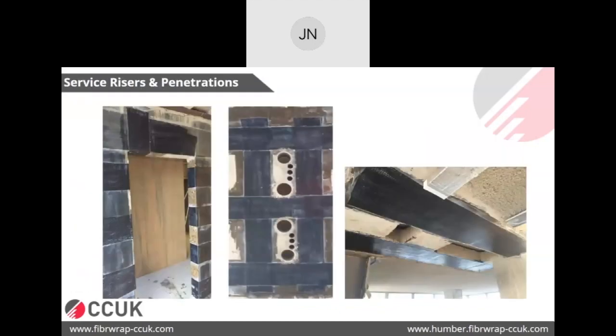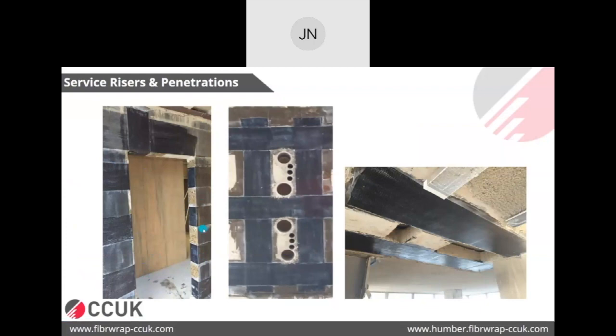Similarly, this is another inquiry we get, which is the service penetrations or riser openings through existing RC slabs or shear cores. So in this case, they wanted to create this door opening through a shear core, and that was strengthened using carbon fiber. Similarly, here they were doing service penetrations through the flat slab, and in that case, they needed strengthening. We all know the traditional solution to do this kind of strengthening is design some trimmer beams, transfer it to surrounding beams, and that's how you deal with this situation. But the same thing you could do with carbon fiber as well, as done in this case.